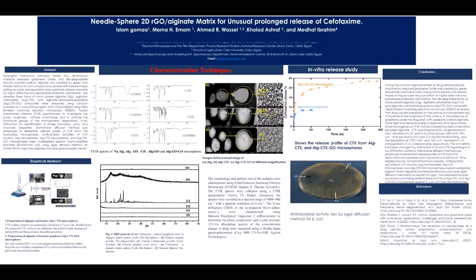alginate cefotaxime, and alginate cefotaxime graphene composite were prepared using calcium chloride as a cross-linking agent and characterized using field emission scanning electron microscopy and Fourier transform infrared spectroscopy to investigate the pores, roughness, surface morphology, and to analyze the functional groups of the microspheres respectively. XRD was employed for the identification of phase formation, purity, and structural properties.